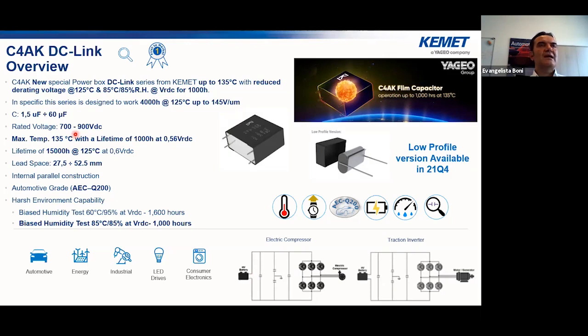The rated voltage is 700 to 900 volts. And at 135 degrees, we can have a lifetime of 1,000 hours at 0.56 rated voltage. But the lifetime at 125 degrees, 0.6, is up to 15,000 hours. It is also a capacitor that is able to withstand 85/85 for 1,000 hours at rated voltage, of course.